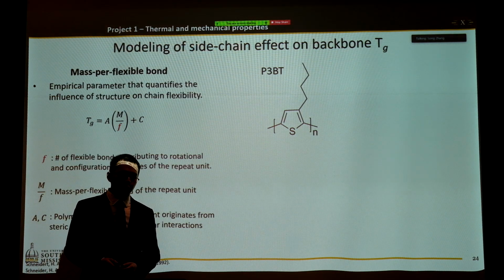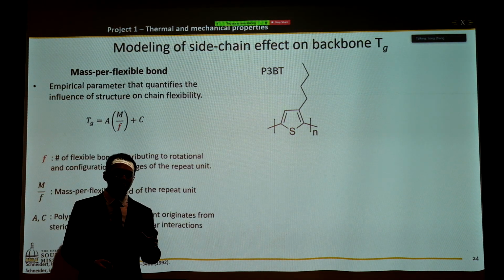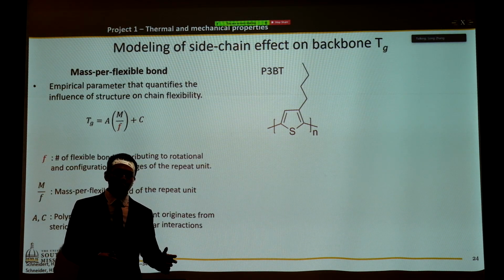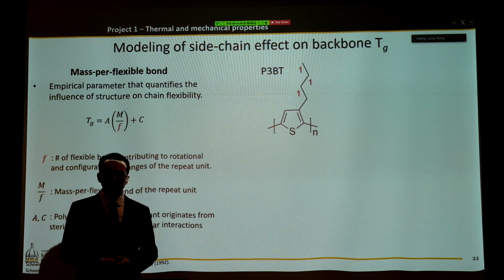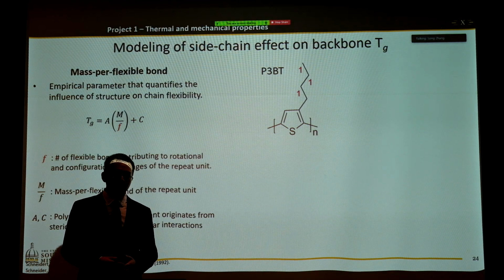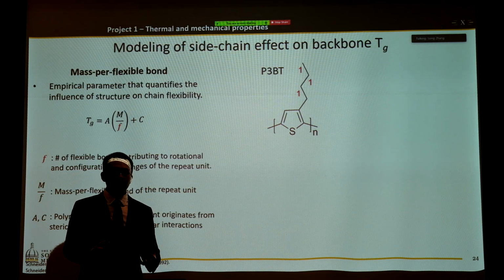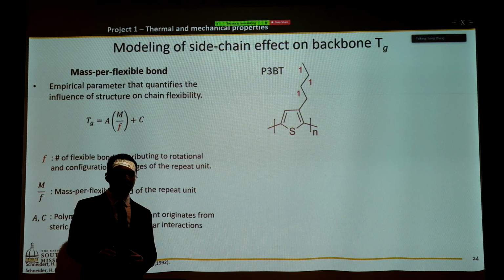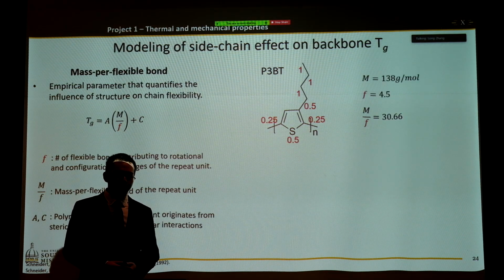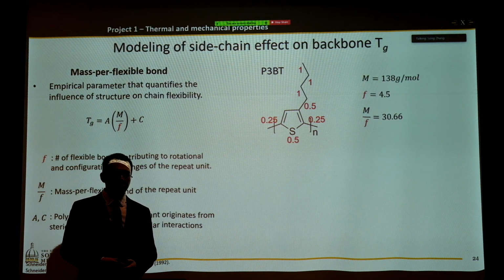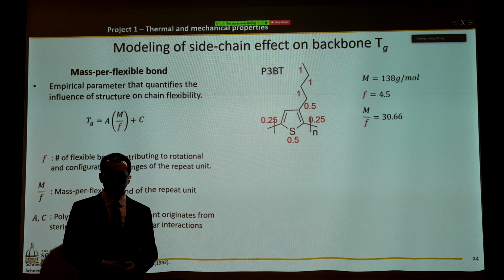So for the P3BT polymer, there is a side chain structure, and we know that each covalent bond of the side chain is very flexible. So on a scale from 0 to 1, we gave it a number of 1. So it has full flexibility, while 0 means it does not have any conformational entropy. However, for the covalent bond that is connected to the thiophene, or the thiophene itself, the conformational entropy is very limited. Okay, let's give it a number of 0.5. With that, the M over F value can be calculated.